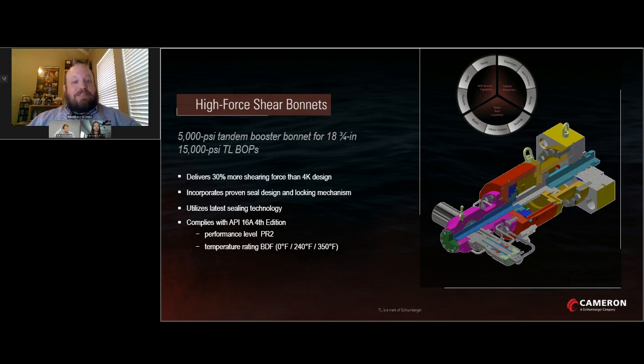Now, much like the ram, this is backwards compatible to an existing BOP stack that would be in the field today, and it actually simplifies the control circuitry because the rigs have a 5,000 PSI control system, and our existing tandem booster was rated to 4,000 PSI, which means we can take out one step-down regulator from 5,000 to 4,000 PSI and just run at 5,000 for it. So we've de-risked a lot of the features, improved the seals, and been able to increase that force. These bonnets are currently in qualification right now at our facility in southern France, and will be available on the market very shortly.